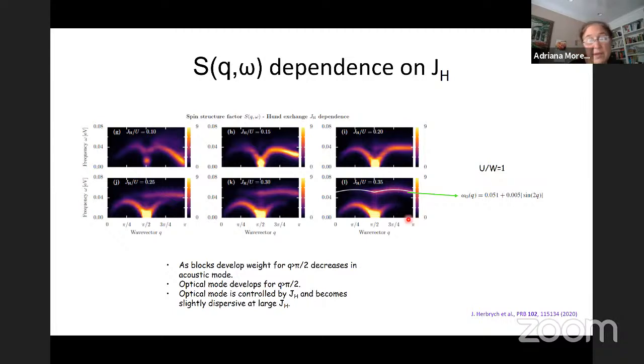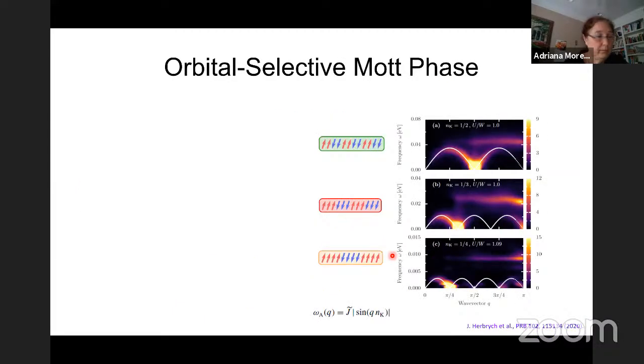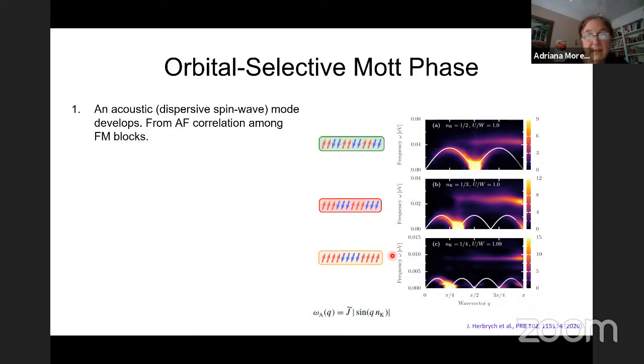So this is kind of evidence of how J Hund controls the position of the optical band. As a result, in the orbital-selective Mott phase, when we have the blocks - we haven't studied this for the spirals - we found that an acoustic dispersive spin wave mode develops from antiferromagnetic correlations among the ferromagnetic blocks.